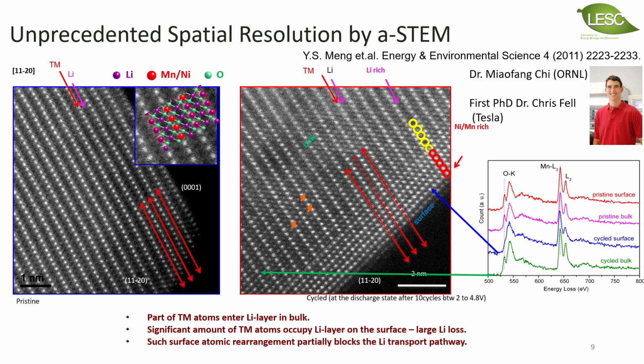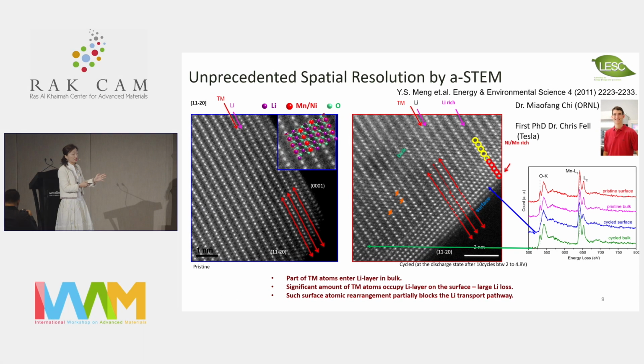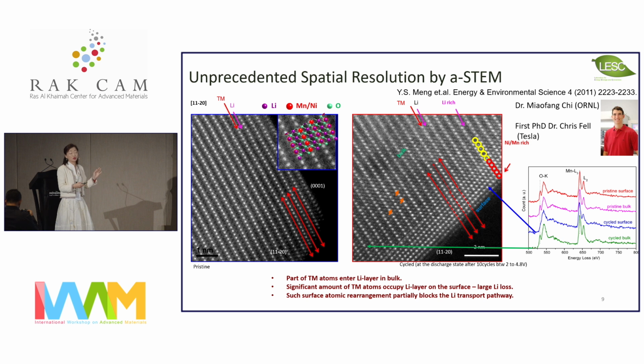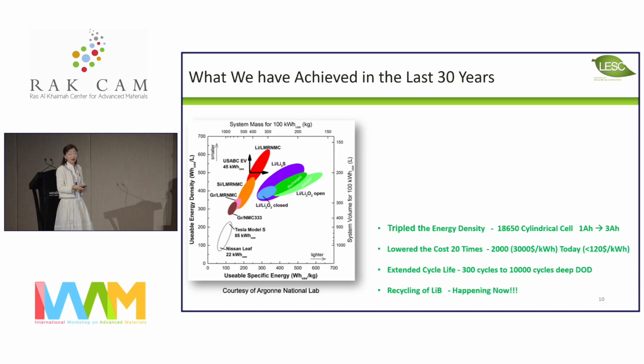And at that time, if you shine an X-ray on this crystal, you cannot tell the difference by X-ray diffraction at all, because it only happens on the surface, 4 to 5 atomic layers. So my student, Chris Fell, who's now super rich because he joined Tesla in 2012. It's always good to see the students do better than the professors, financially especially. So he actually proposed that all the cathode materials should have a surface coating to protect the surface of the cathode. So this is one of the first results, I would say, to help industry understand the degradation, and then the knowledge we generated was very well utilized in the industry.